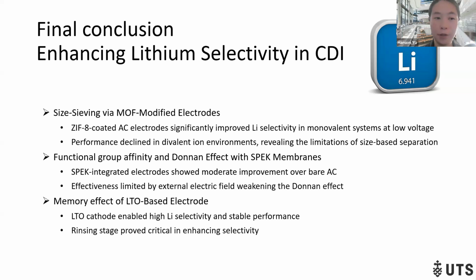Strategy 1, size-sieving via modified electrode: the ZIF-8-coated AC electrode significantly improved lithium selectivity in monovalent cases at low voltage. The performance declined in divalent ion environments, revealing the limitation of size-based separation. And strategy 2, the functional group affinity and Donnan effect with SPEK membrane. It shows the SPEK-integrated electrode has a moderate improvement over bare AC electrodes, and the effectiveness is limited by the external electric field, weakening the Donnan effect. And in strategy 3, the memory effect of LTO-based electrodes, we found the LTO cathode enables high lithium selectivity and stable performance. The rinsing stage proves critical in enhancing selectivity.